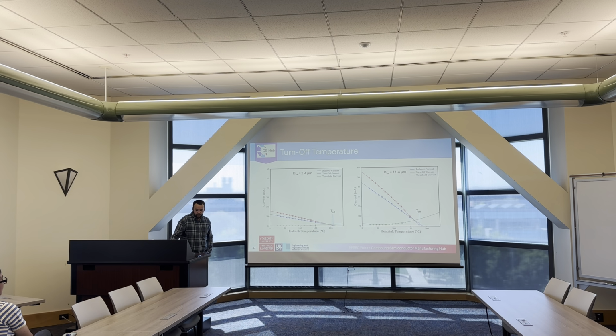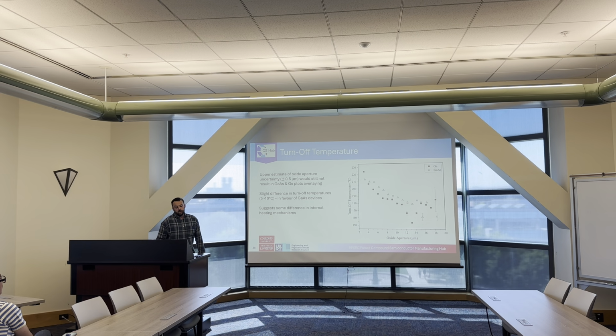But I looked at it as well as a function of aperture size, expecting it to be constant, but actually finding that you have a lot flatter variation with temperature, say turn-off and rollover, for a small aperture device, which pushes out that turn-off temperature compared to a large device, which drops off really rapidly. So when I plot it all out, we get clearly a decrease as a function of oxide aperture, and then just revisiting the story of GaAs versus germanium, even if you account for the variation, the 0.5 micron uncertainty in the oxide aperture, the plots probably won't really overlap. So there could be some difference in the internal mechanisms.